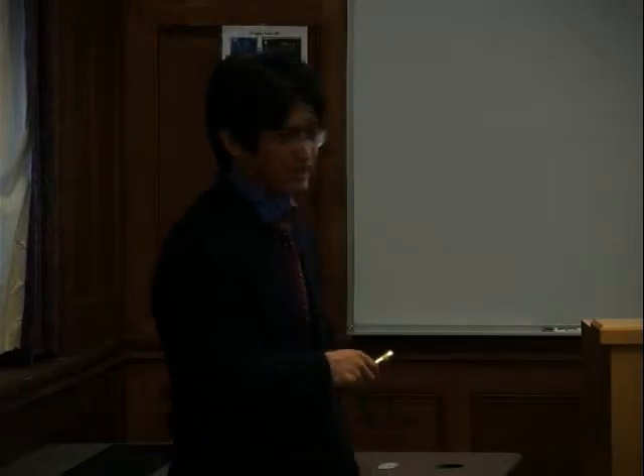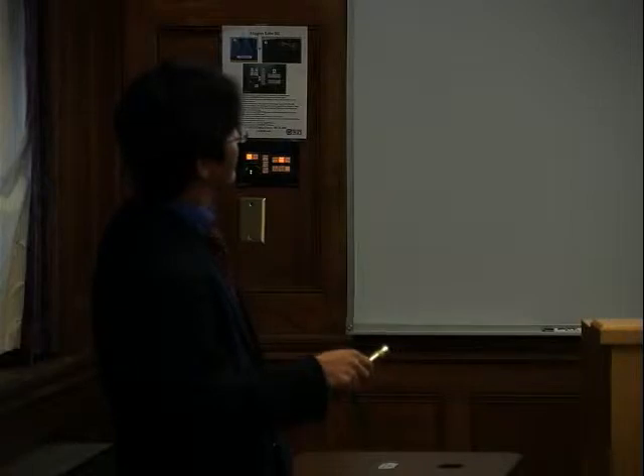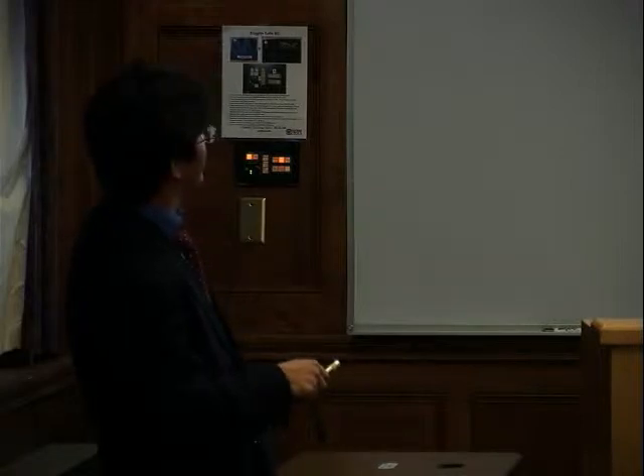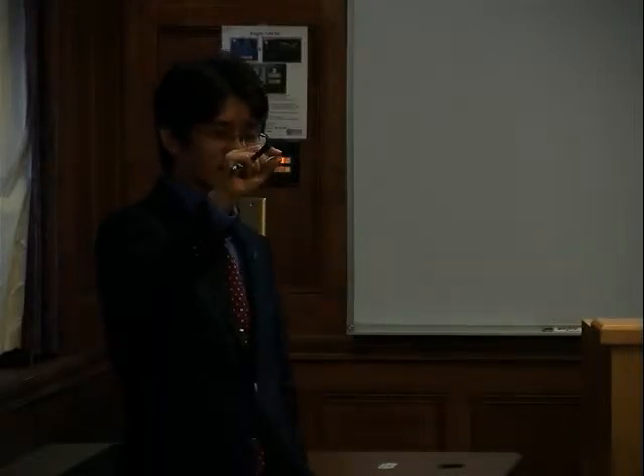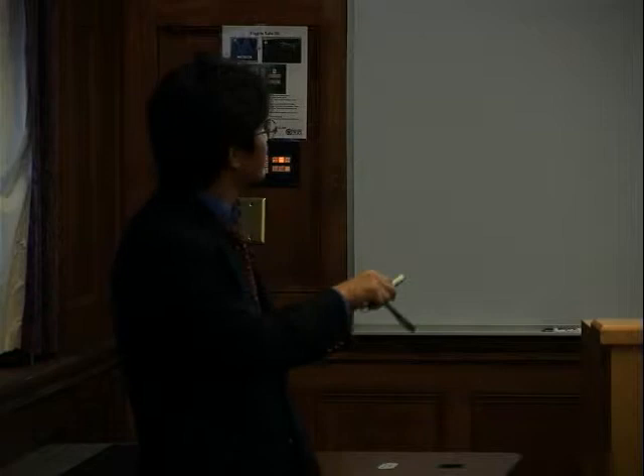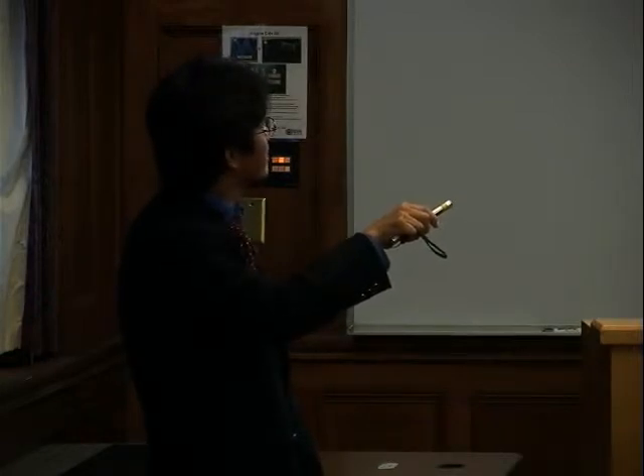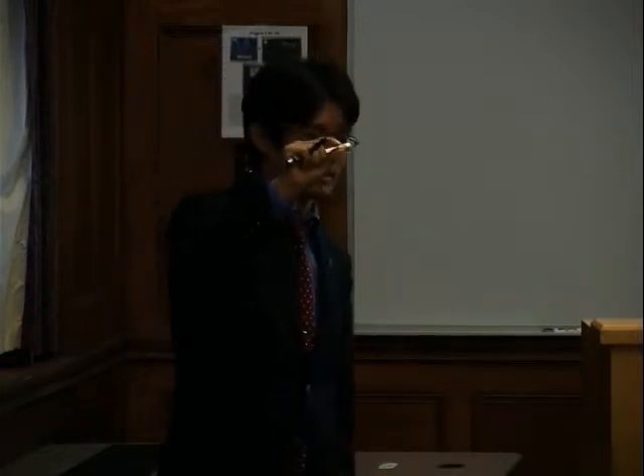Now let me talk about the results of the base case, nickel chrome 0.8, which means that the inner core is made of nickel chrome. The outer diameter of the nickel chrome is 0.5 millimeter. The thickness of the polymer coating is 0.15 millimeter. It's very, very thin. This is the base case. Let me talk about the results of this base case.